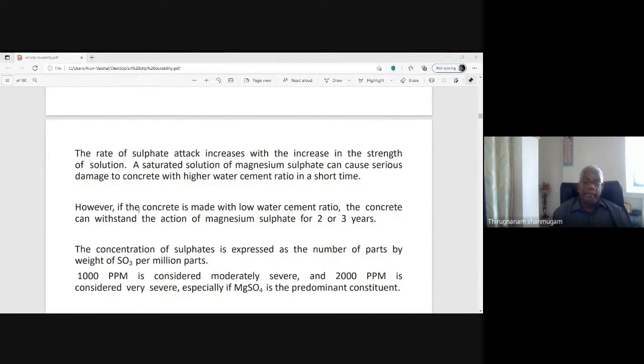The concentration of sulfate is expressed as the number of parts by weight of sulfate SO3 per million parts. 1000 ppm is considered moderately severe, and 2000 ppm is considered very severe, especially if MgSO4, magnesium sulfate, is the predominant constituent. So the magnesium sulfate salt is normally coming through the water. So the water is strictly subjected to quality control. If the mixing water or curing water contains more than 1000 ppm of sulfate ions, then it should not be used for the mixing or curing, because it is considered moderately severe, and if it exceeds 2000 ppm, very severe, causing deterioration of the concrete.